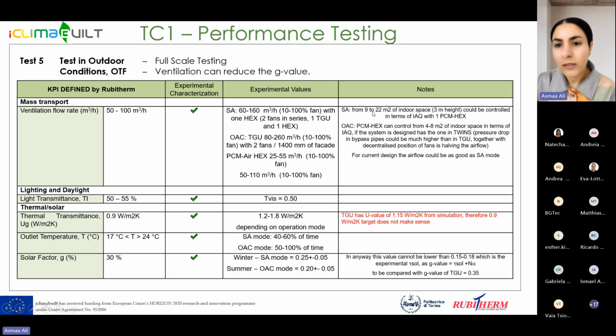So as I said, 9 to 22 square meters of interior space can be ventilated with only one PCM heat exchanger. However, for outdoor air curtain mode, the number was half, and this could be due to the pressure drops developed across the pipes. This, of course, can be improved, however, it is still sufficient and within the predefined KPIs. And the light transmittance was found to fall into the range we also defined, about 50%. The U value was found between 1.2 to 1.8.